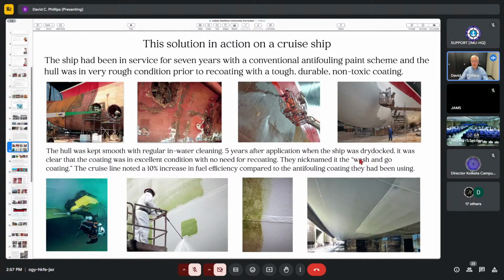Actually, the officers and crew of these ships nicknamed this type of coating the wash and go coating, because they would arrive in dry dock, it would get washed down, they'd touch up any mechanical damage, a few liters of paint to touch up the mechanical damage, and that would be that. They could sail, as opposed to the usual situation in dry dock, which is more like this, where you have to recoat every 2.5 or 5 years or whatever it is. The whole coating has to be either patched up and the top coat replaced, or you have to redo the whole coating. So this is a different approach. It stays on for the life of the vessel.